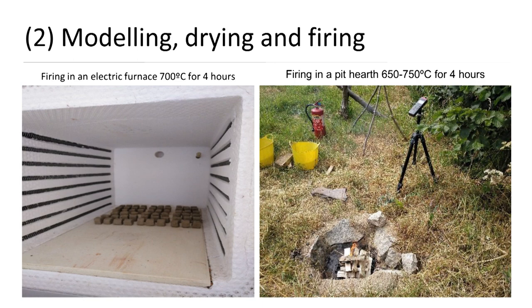The reason for these two different types of firing is that almost all of the experiments on technological properties in archaeology use only an electric furnace for firing the samples, as it is generally considered that in this way, more consistent results are obtained. However, we considered it interesting to use these two different methods to compare and also test whether this assumption is true.